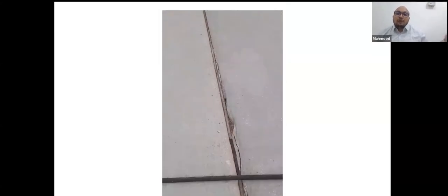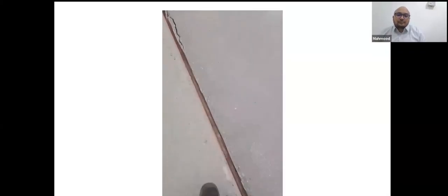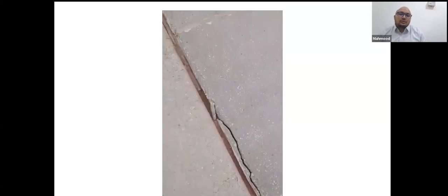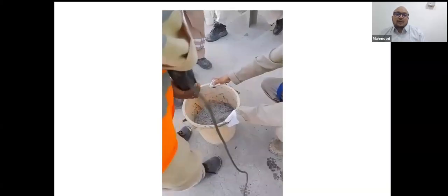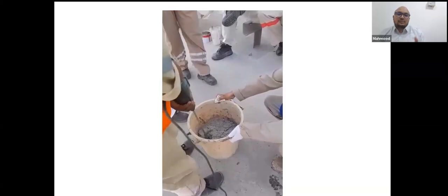Now we'll see the edge repair on an open pond on a big oil field. Some repair has to be done if the edge breaks. You need to do repair with a high strength epoxy repair mortar: base, hardener, and then filler. The filler will be like silica sand and flakes, based on the requirement.